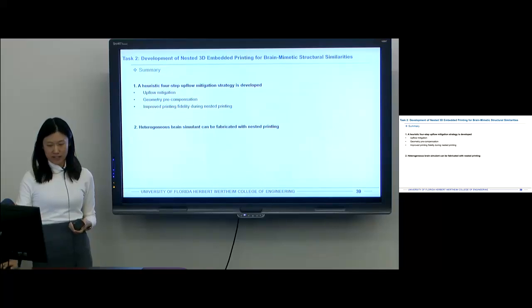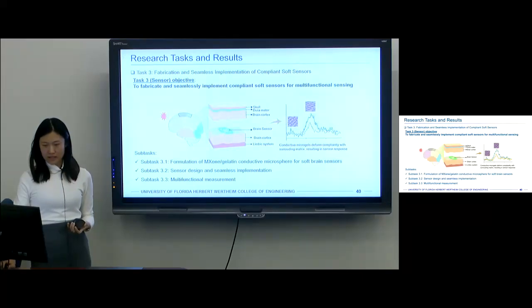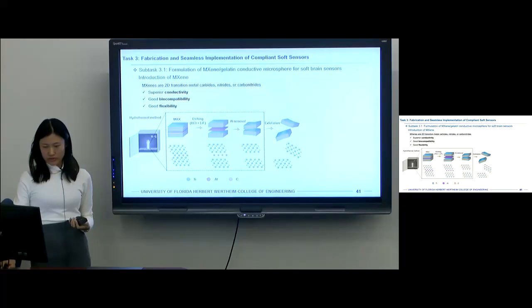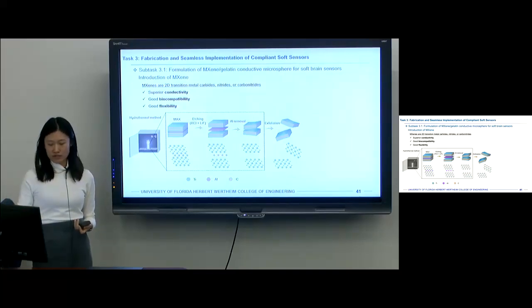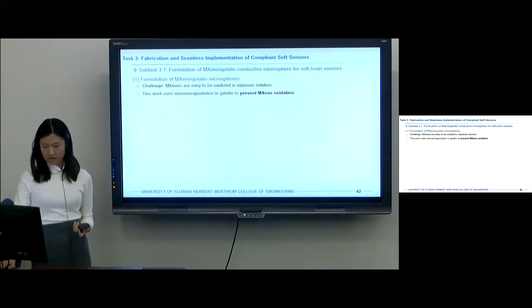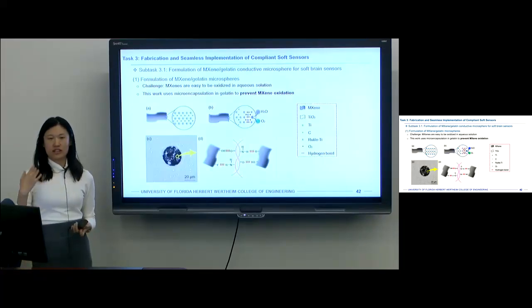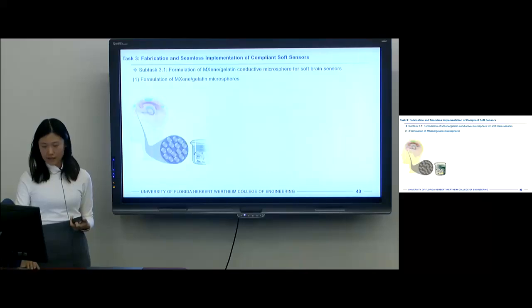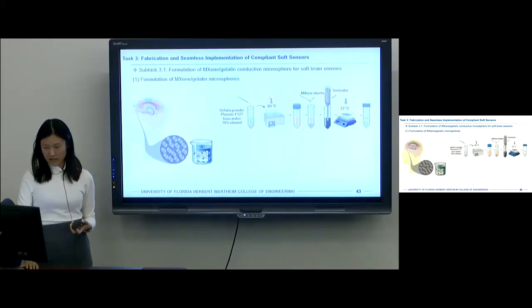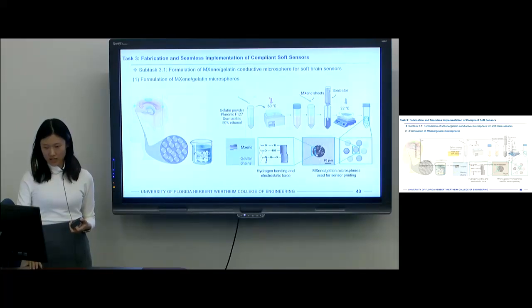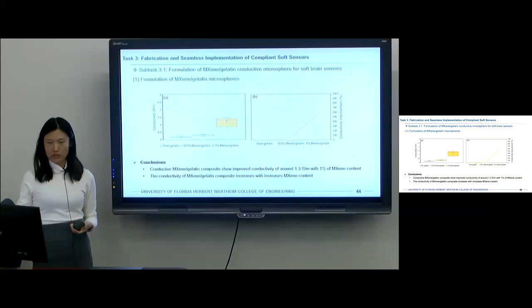So in this section, we developed a mitigation strategy and printed the brain simulant with high shape fidelity. The next task is to fabricate the sensors inside of this brain simulant. We used a material called MXene, which is a very conductive 2D material. MXene is usually prone to oxidation, especially when working in a liquid environment such as the brain. So we applied an anti-oxidation process, using gelatin to encapsulate the surface. This can prevent the oxidation of the material, and the material can still be conductive.